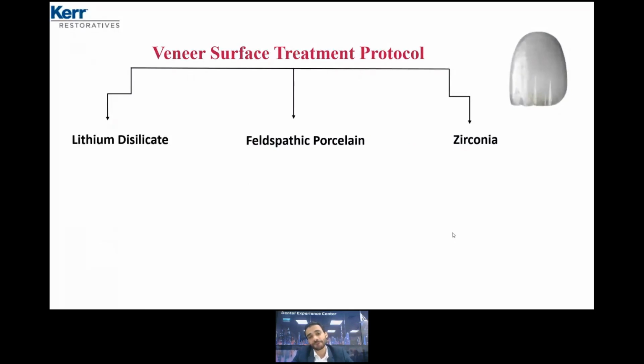For the lithium disilicate, like Emax, you need first to acid etch using hydrofluoric acid for not more than 20 seconds. Why? What will happen? With more than 20 seconds, most of the articles claim that you can have a ceramic dust. And actually the ceramic dust will cover the porosity that you get from the hydrofluoric acid, which means it will affect the bonding strength. So please don't apply the hydrofluoric acid for more than 20 seconds on the lithium disilicate.